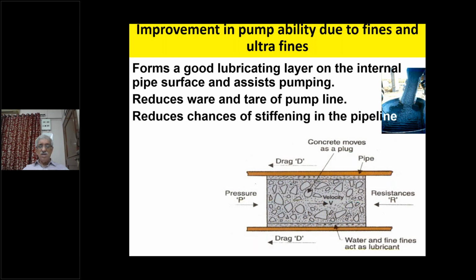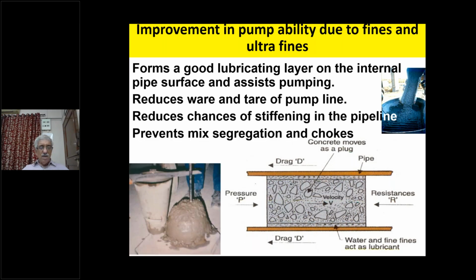Another thing: it reduces the chances of stiffening in the pipeline. If there is a problem with the pump or the batching plant and the supply is not there, you can still wait for some time and give a gentle stroke every 10 or 15 minutes so that the initial viscosity is not there. And when you resume the pumping, it will give a smooth flow.